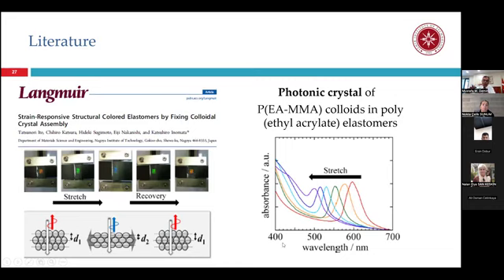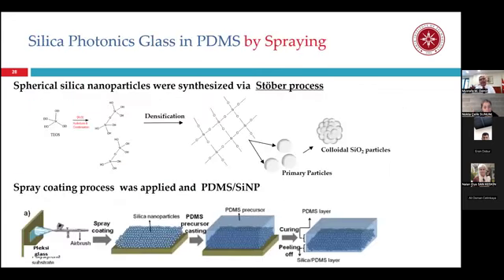So when you apply force, since this spacing changes, you are in the limit between 150 and 300, so it is possible to give color, and if the substrate is elastic, it's supposed to return back to the original color. In our case, we took the opportunity for the synthesis of silica particles using the Stoeber method. The Stoeber method has been known for more than several decades in literature.